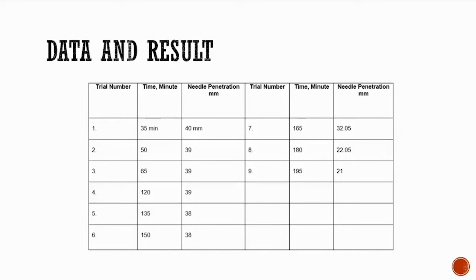In the data and results of this report, we have 9 trials. Trial number 1, time in minutes 35, and needle penetration 40 millimeters. In trial number 2, time 50 minutes, needle penetration is 39. Trial number 3, 65, needle penetration is 39. Number 4 is 120 and 39. For number 5, time is 135, needle penetration is 38. Trial number 6, time is 150, needle penetration is 38.